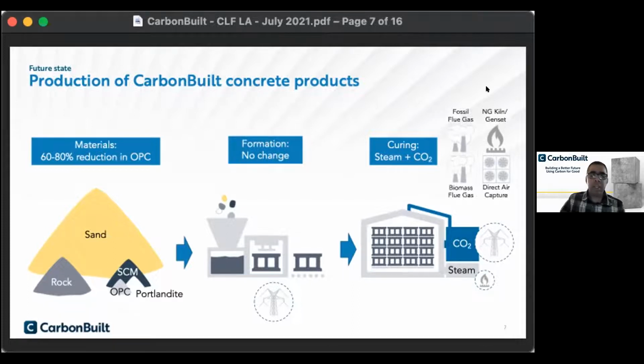Okay, and it's important to note here that everything we're talking about is happening during the curing process. Okay, so this is very distinct from the long duration carbonation that many of you may be familiar with, that happens over decades, where residual calcium hydroxide in concrete reacts with the CO2 in ambient air, right? That's a very slow process, converts very little of the calcium hydroxide, and it happens over long periods of time. Here we're talking about reacting CO2 at elevated, but not pure, concentrations over a matter of hours to create lots of calcium carbonate, which delivers strength.